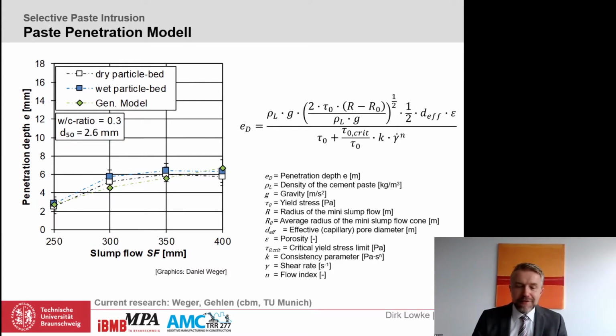In recent years, this process was intensively investigated by Daniel Weger, and you can see some results of his work here. The aim of his work was to connect the rheological properties of the cement paste with the penetration depth in an analytical model. This diagram shows results, and you can clearly see that, as expected, the penetration depth increases with increasing flowability of the paste. You can see his final model on the right-hand side, which is based on the Chevalier model, and it captures the yield stress as the main characteristic of the fluid phase, as well as the porosity as the main characteristic of the particle bed.